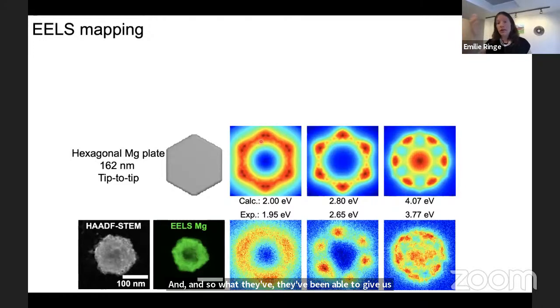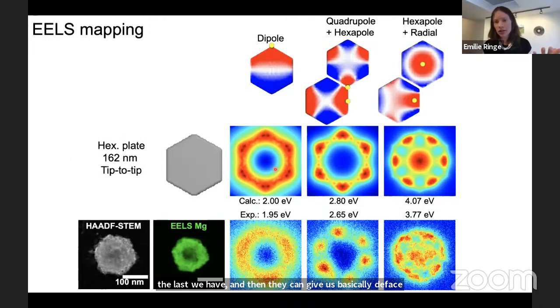What they've been able to give us are theoretical maps of loss, and I'm pretty convinced these match really well with the loss we observe. Then they can give us the phase of that electron oscillation, from which we can diagnose which modes these are. This is a little bit more complicated than for a simple sphere. The first mode, not surprisingly, is a dipole - wherever you put your beam around the particle, you'd excite this dipole and get the donut shape. The second mode turns out to be more complicated because it's actually a combination of two modes that are very close in energy.